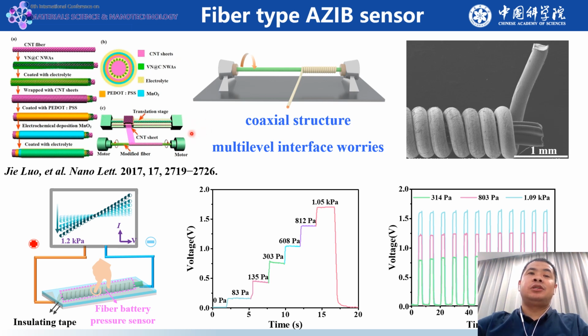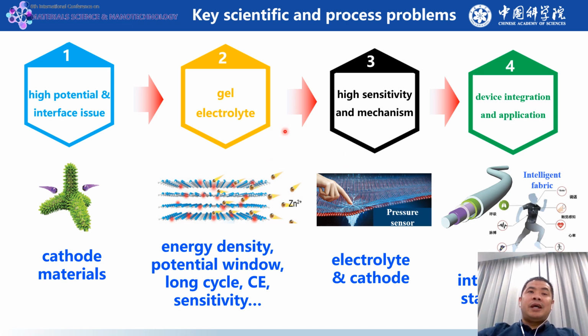As you can see, a homemade machine was used to construct a one-body coaxial structure device. This device presents high sensitivity at different pressures, and it also presents a rapid response and recovery rate. Despite these advantages, for the long-time cycle life, the multi-level interface stability needs more work. In conclusion, several aspects such as the cathode materials interface issue, the hydrogel electrolyte, as well as the sensing mechanism also need further investigation. And especially the device integration and application also need help from an experienced team. Welcome anybody to offer some ideas to help us solve these problems.